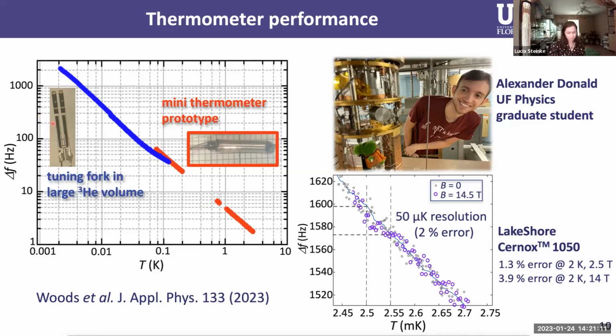And what this shows is that this is a really good thermometer, and that I can measure temperature from the resonance width over more than 3 decades, over more than 3 orders of magnitude. And I have an extremely predictable 1/T temperature dependence. So I might not even have to calibrate it.